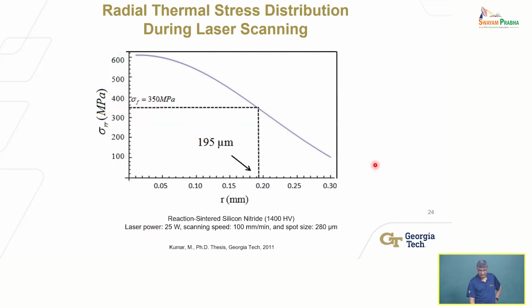And this is the distribution predicted by that analytical model for the Gaussian temperature distribution, the energy distribution that you're providing as input, as a function of radius, the distance away from the center of that circular region that is being irradiated. And you can see that it says you will produce fracture stresses at least equal to 350 megapascals up to 195 microns from the center. So within a radius of 195 microns, I should generate thermal stresses that exceed or are equal to the fracture strength of this material.